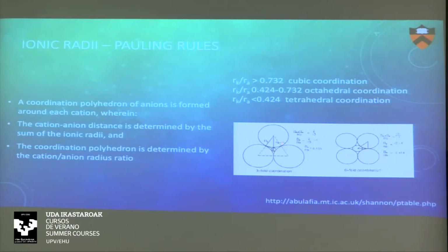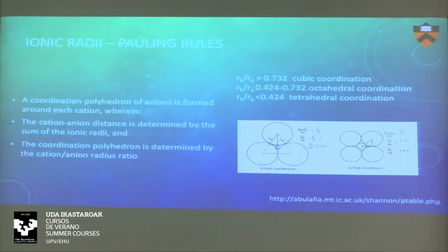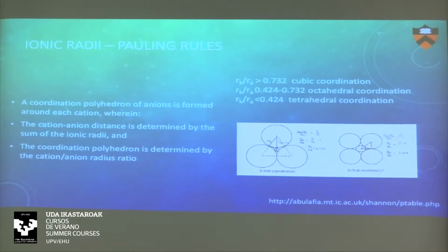And then you can calculate the size of a hole between all your atoms. And from this you can derive some ratios of cation to anion radius and see what kind of coordination is possible so that your cation literally fits in the space of the anion. So your anion is always the big one. It fills the space. The cation goes in the small holes. And you can really calculate, does it fit? And so you get these numbers.